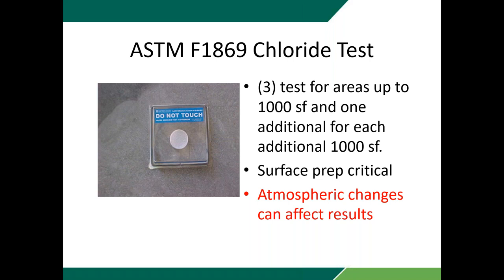Another reason is, much like the visqueen test, both of these tests are measuring moisture vapor transmission out of the concrete. And as we get into talking about moisture vapor transmission, you're going to find that a good deal of what determines the rate at which moisture is coming through the concrete is the atmosphere in the room. So I can literally change the results of this test simply by changing the atmospheric conditions in the room, changing the relative humidity in the room and things like that.